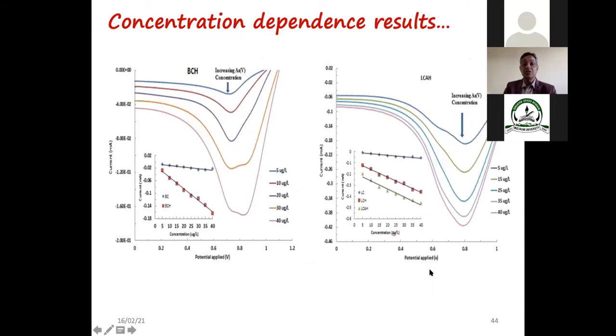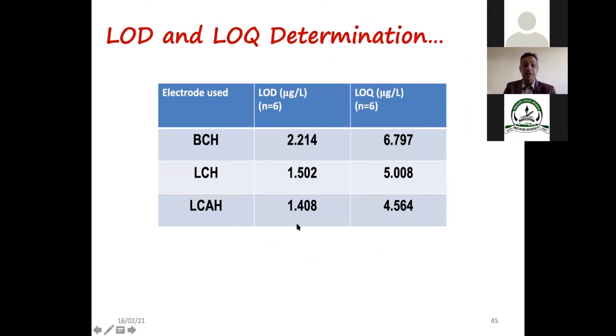And this is the concentration dependence data that we obtained. We increased the concentration of arsenic 5 using BCH or LCAH, and we get a good correlation. Then we calculated the LOD, limit of detection. For BCH we get 2.214, but LCAH gives a much lower limit of detection, almost 1.4, much lower than that.